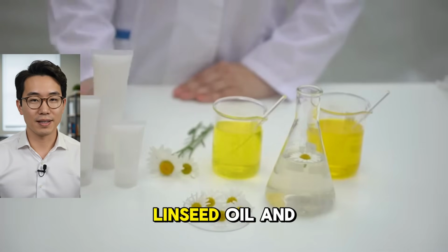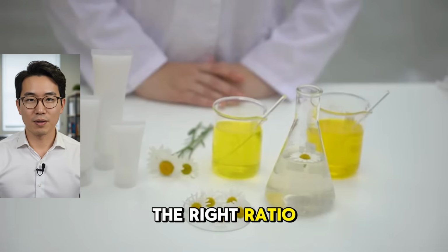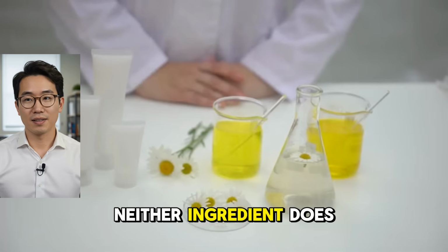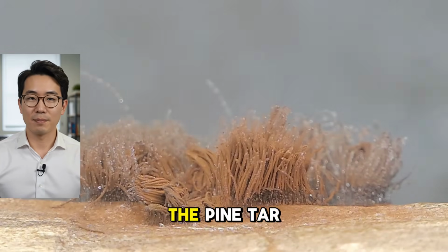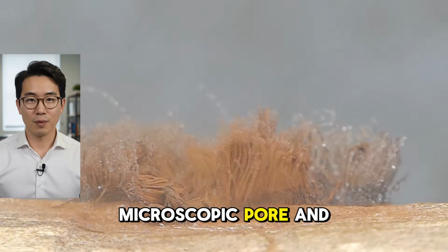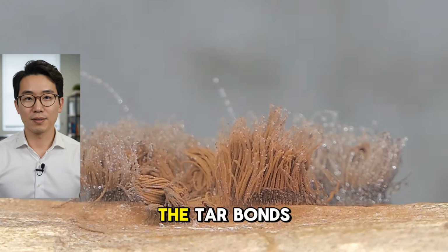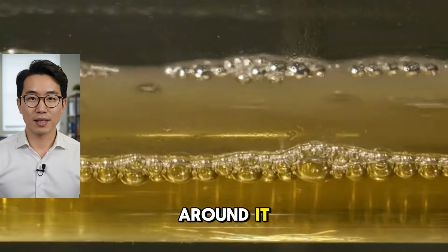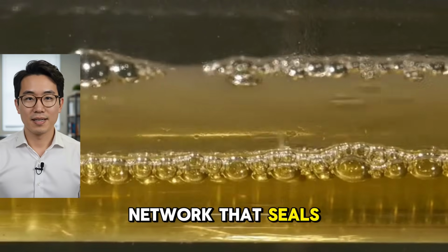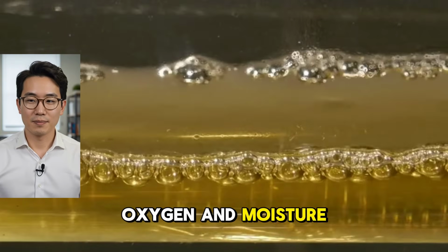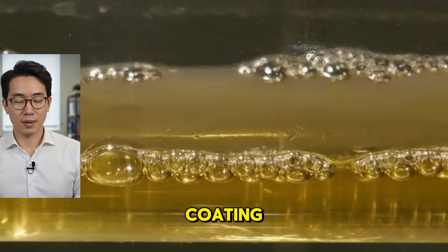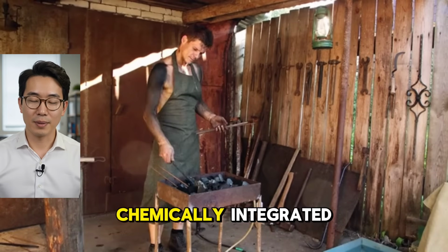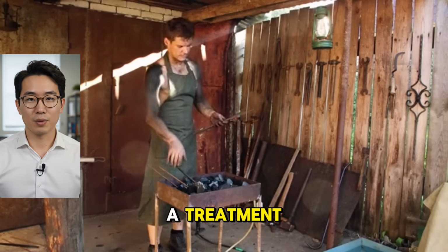When you combine raw linseed oil and pine tar in the right ratio, something happens that neither ingredient does alone. The linseed oil carries the pine tar deep into every microscopic pore and pit in the metal surface. The tar bonds. The oil cures around it, forming a flexible polymer network that seals the metal from oxygen and moisture, not on top of the surface like a paint or a coating, but inside the surface. Chemically integrated, not a barrier, a treatment.